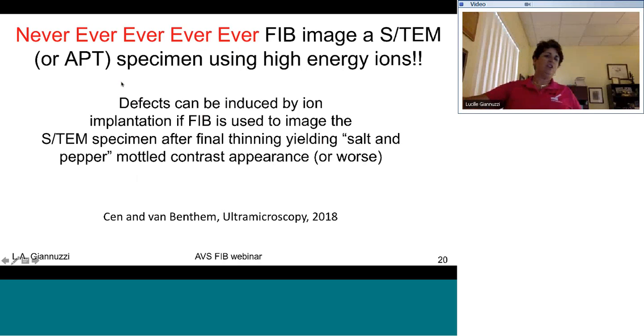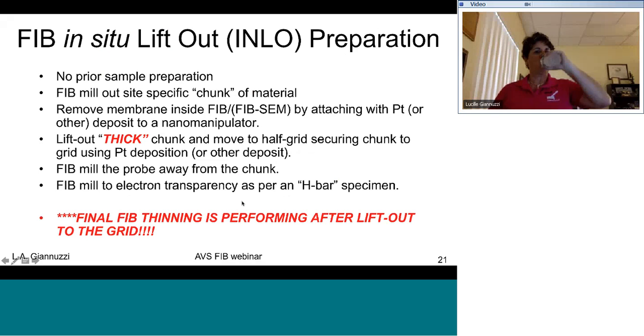Okay, the one thing that I talk about when I do this lecture on FIB-TEM sample prep is never, ever, ever. You don't want to FIB image your final TEM specimen using your high energy ions or ions in general. Why? Because as I showed with the simulations earlier, you can induce defects and you can get ion implantation just by imaging this sample. So once it's finished, you don't want to image your sample, and I'm going to show you some work by this group, which illustrates just that in a little bit.